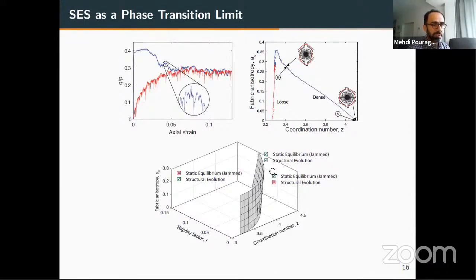So on the right-hand side, we have a static equilibrium, but a structural evolution, the global structural evolution, is not possible. On the left-hand side, if you manage to cross the threshold, it seems that the sample becomes unjammed. The structure can evolve, but there is no static equilibrium. It's only along the surface that you can have them both. You can have a static equilibrium and a structural evolution. And actually, we'll see later on that this is a going back and forth between the two regimes because of these sort of micro avalanches.